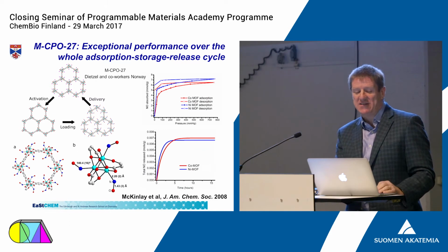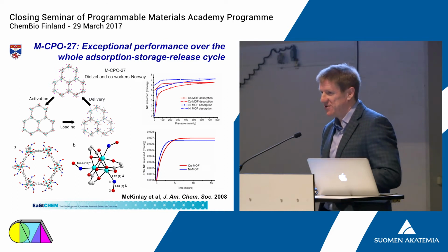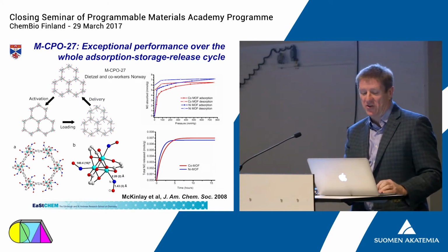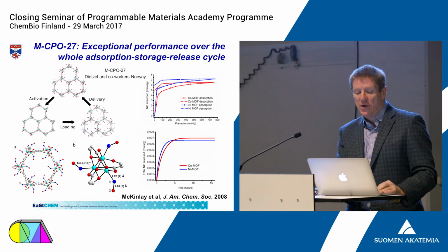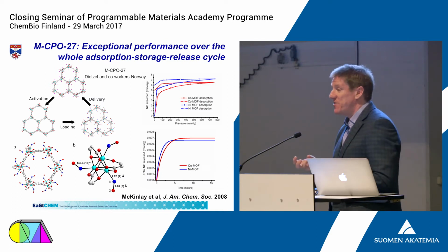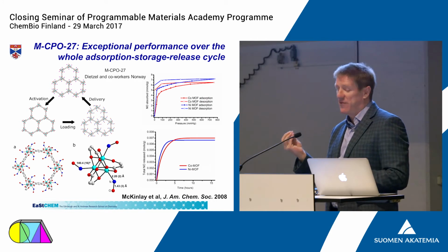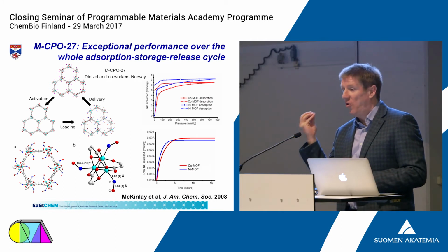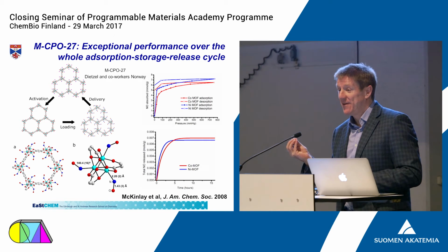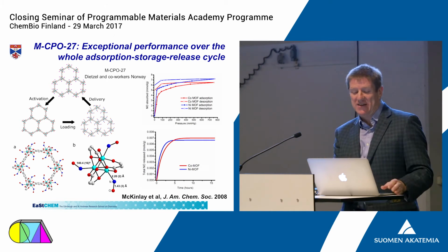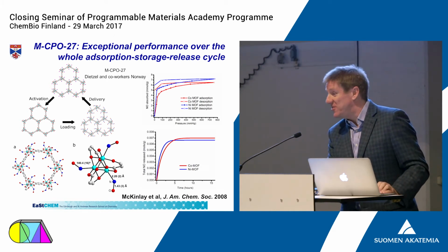So we activate it, we dehydrate the material, then we load nitric oxide on. The nitric oxide sticks to that metal in the corner, and we can do the crystal structures and find out what it looks like. And then we can expose it back to water, and it delivers it. And the great thing about these materials is they deliver all of it. So it's a perfectly good release, and in very, very large amounts.